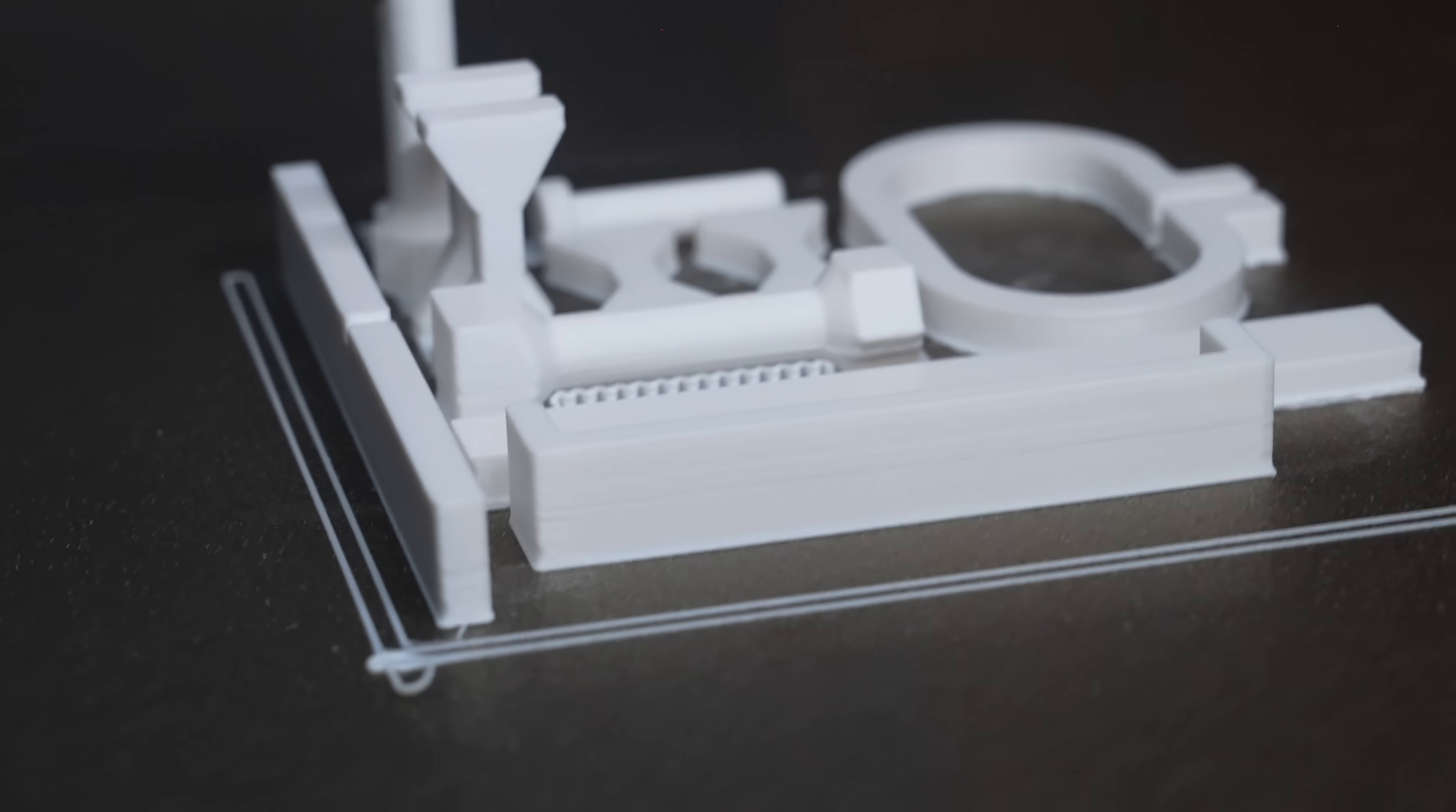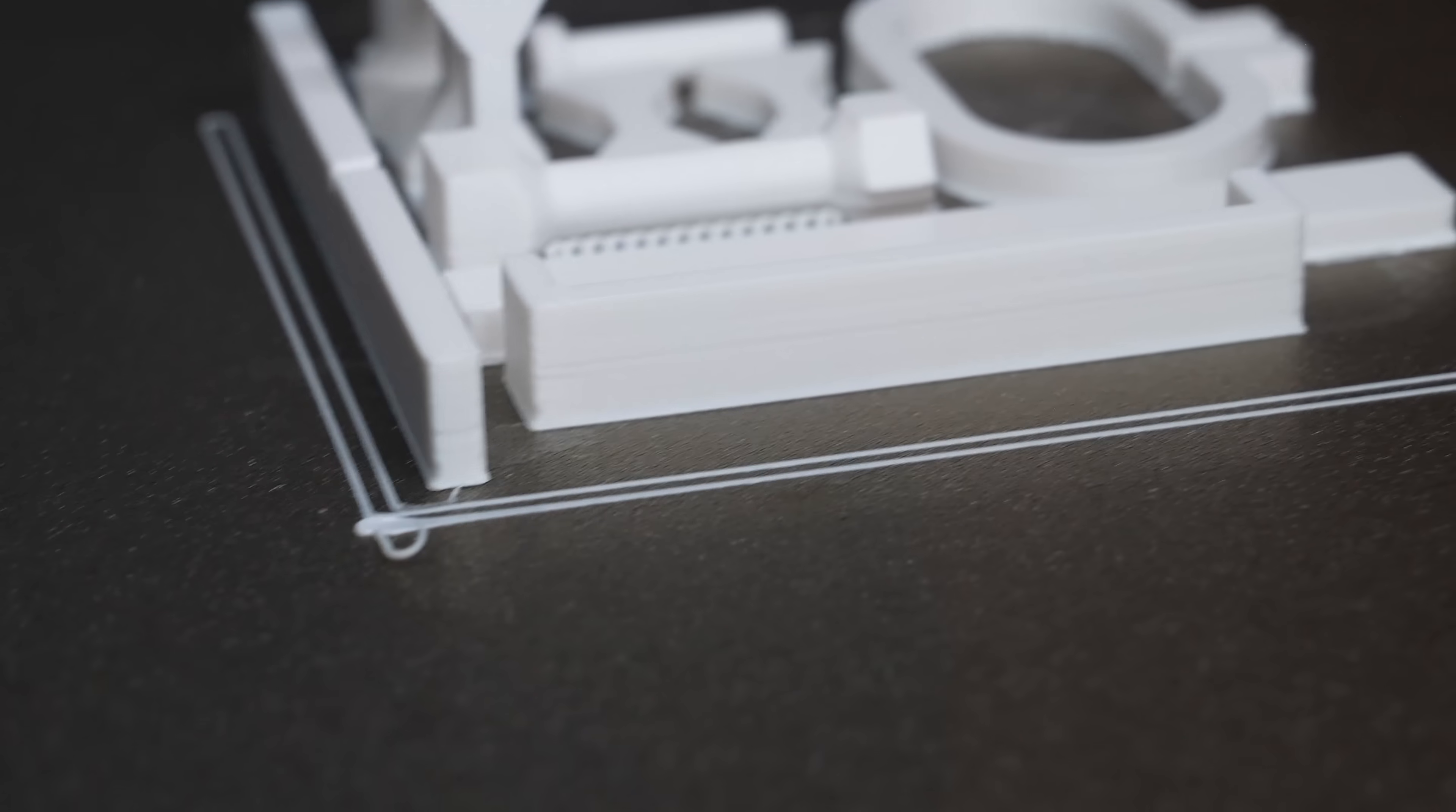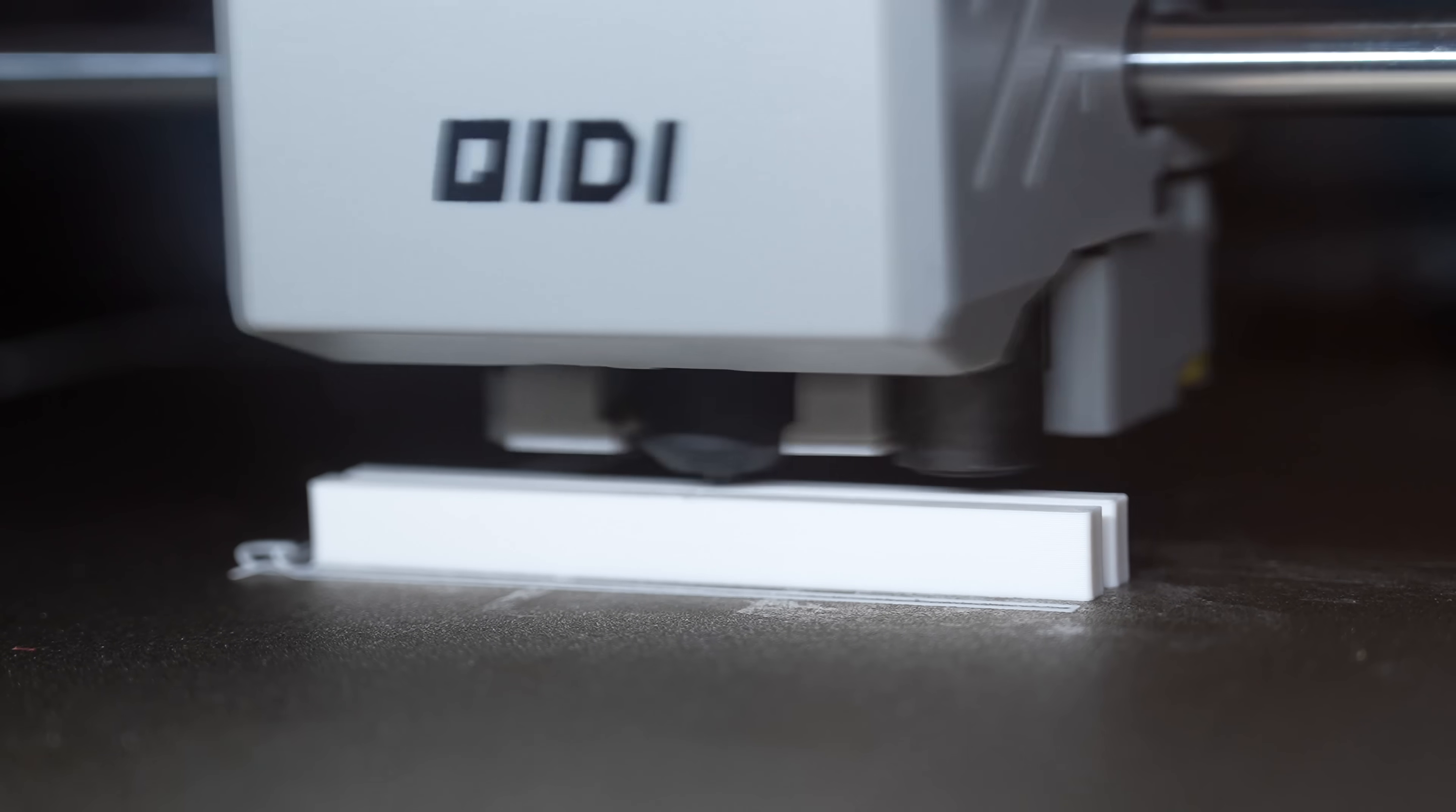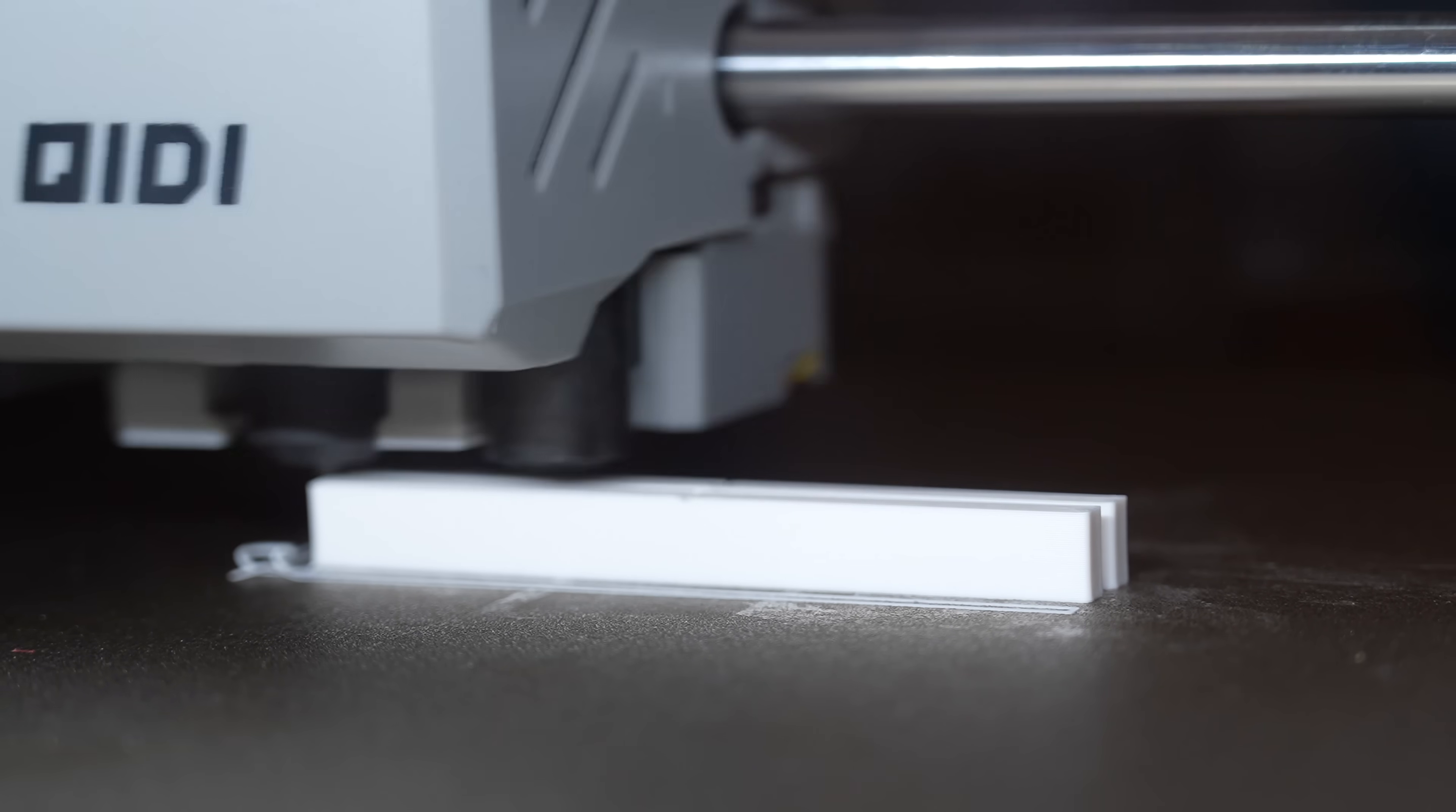The printing is finished and I hope you can see this elephant foot too. This is my first printing on 100 degrees Celsius bed. Maybe it doesn't compensate enough because maybe the homing was done on lower bed temperature. I noticed that if I preheat everything, the bed and a little bit the chamber, the Z offset is set correctly and there is no elephant foot.